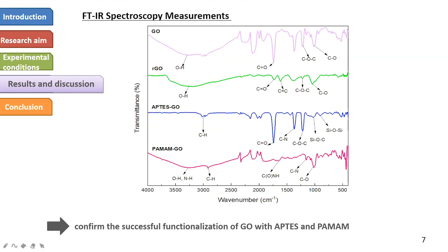New bands become visible after interaction of GO with APTES around 1000 centimeter on -1. This signal appears, the silicon oxygen carbon here. And the silicon oxygen silicon absorption peak shows the reaction between the APTES molecules. Nevertheless, the vibration of hydroxy groups disappear in APTES GO samples, which corroborates the fact that the ethoxysilane groups of the APTES react with the hydroxyl of the GO.